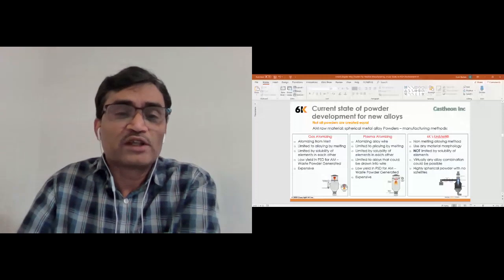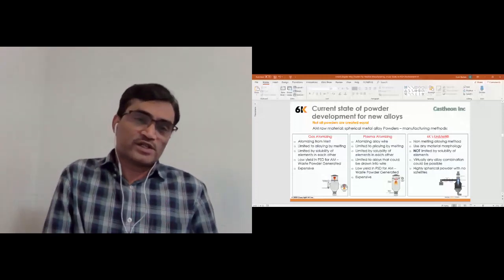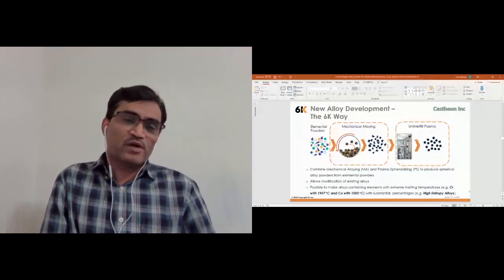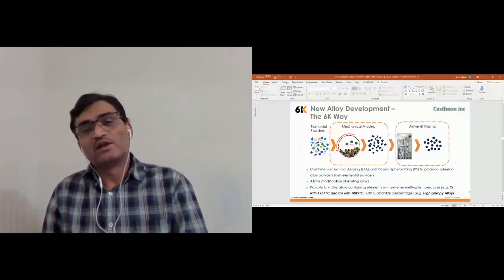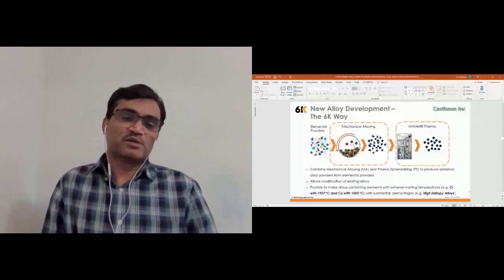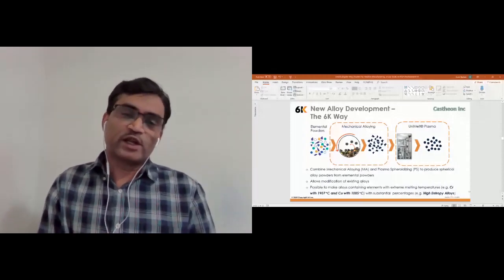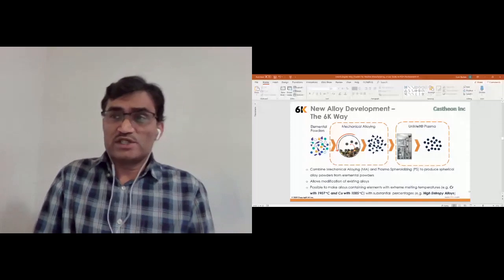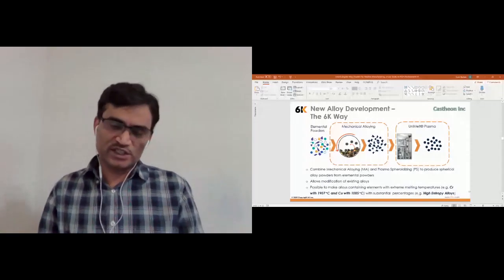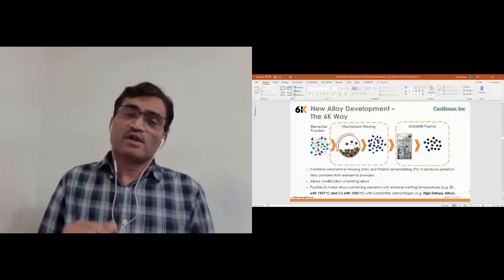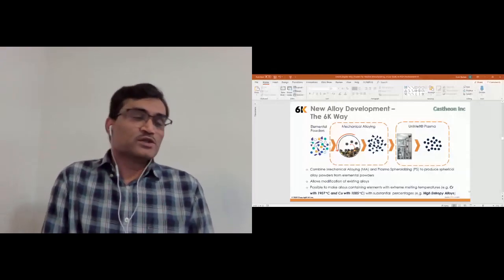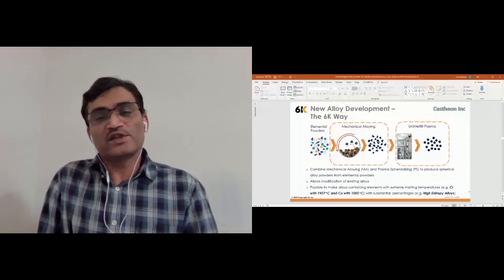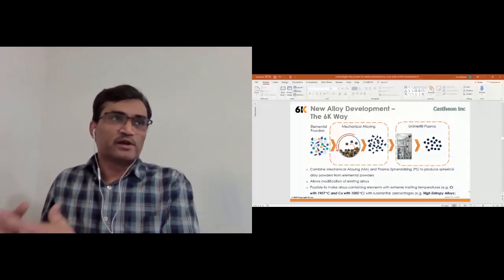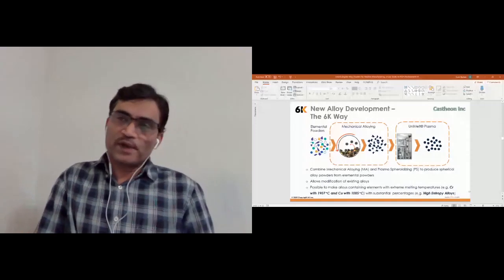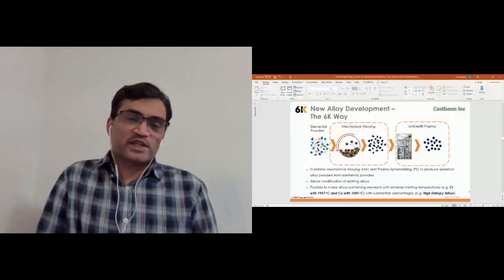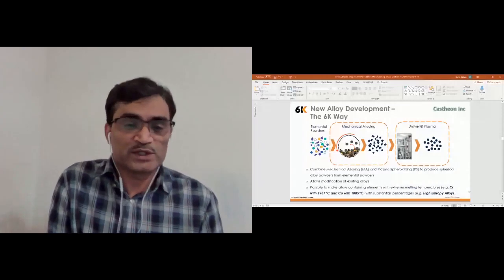Instead, we can combine mechanical alloying technology, where you use different elemental powders and make the alloy by mechanical alloying. The result of mechanical alloying, of course, is a powder with a flaky, very irregular shape with very low apparent density, which is not useful for any commercial processing technologies that we know right now. Then we can use that powder with the 6K UniMelt technology and produce a perfectly spherical, dense powder, which can be used for various technologies like additive manufacturing, MIM, or hot isostatic pressing.